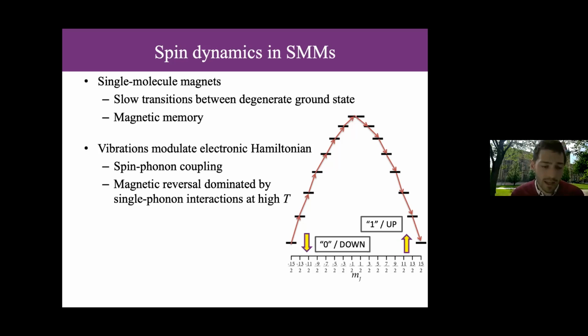And so if you're taking, let's say, the average coordinates and you do an electronic structure calculation, you obtain the average, or the time average wave function. But of course, the instantaneous perturbations by distorting your atomic coordinates is how your vibrations lead to spin phonon or vibronic coupling. So in this talk, spin phonons and vibronic coupling, I'm going to use synonymously, because in reality, in